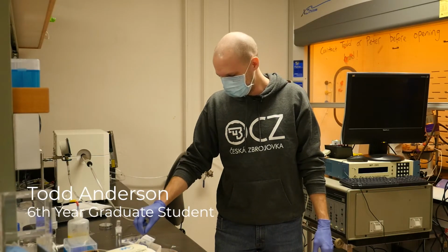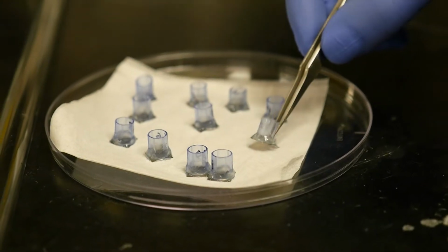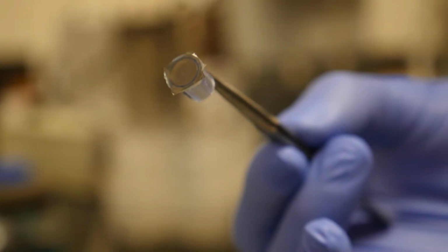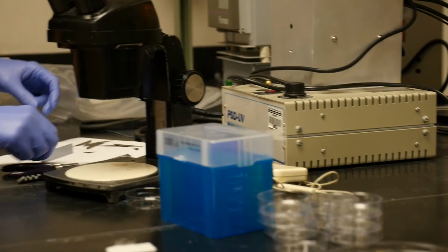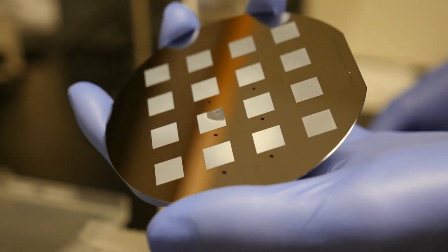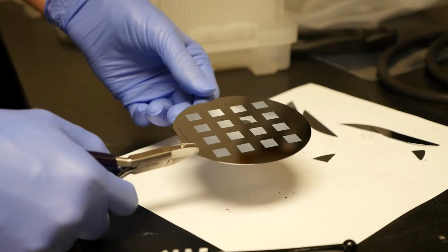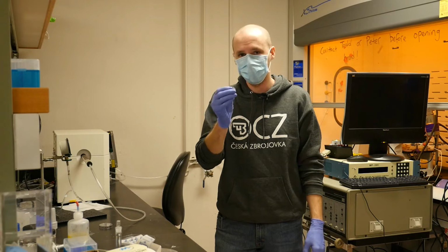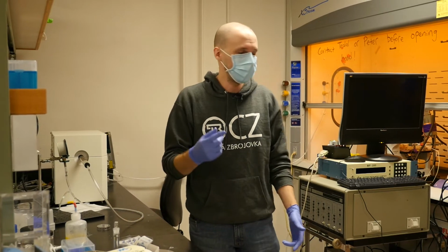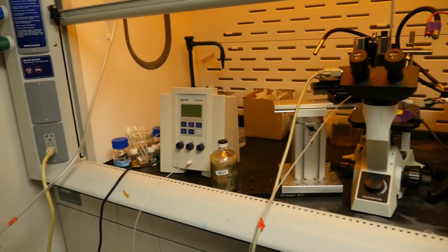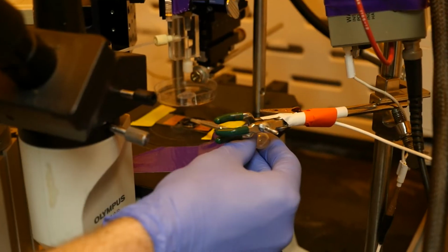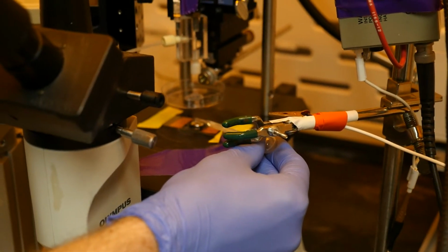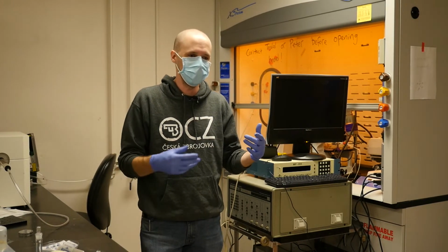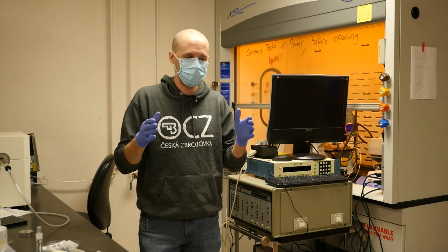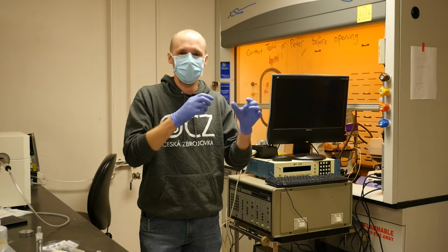I primarily work with these carbon bipolar ultramicroelectrode arrays that I fabricate in a clean room here on campus. These are made up of about 150,000 different 8-micron carbon electrodes that are embedded in a polymer membrane. I'm using these right now with this setup over here to electrodeposit a gradient of catalytic metals across the surface. So what this allows us to do is very, very highly parallelized screening of the electrocatalyst that is deposited on